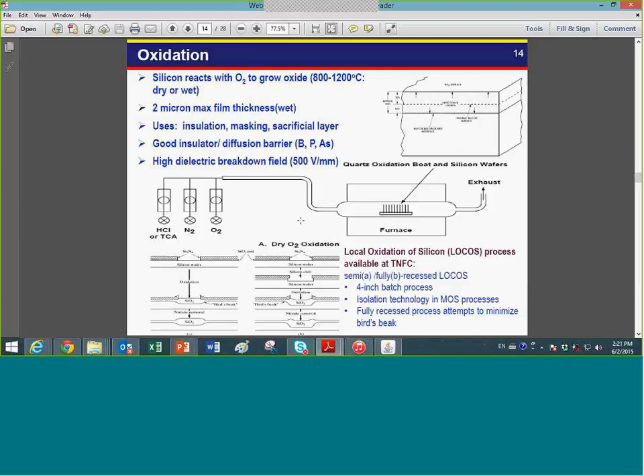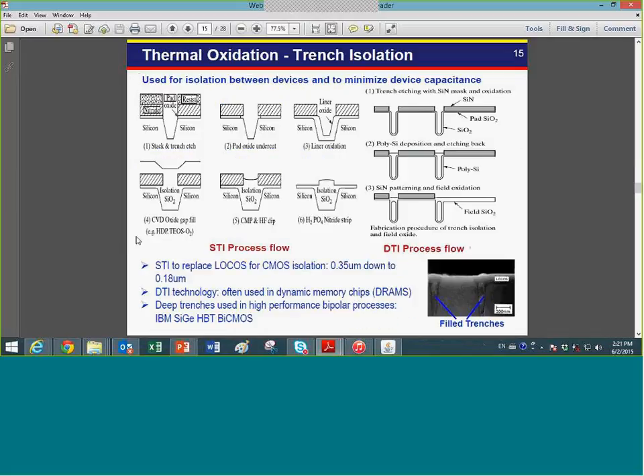And for oxidation, we have a furnace here that can do batch processing of oxidation for 4-inch wafers. We can do the LOCOS process, the semi or fully recessed LOCOS process, which is still a very important process for either optical or circuit applications. But below 0.3 microns, usually you are not going to use the LOCOS process. Instead, you will use STI or DTI isolation techniques to isolate the transistors from one another to avoid latch-up events.